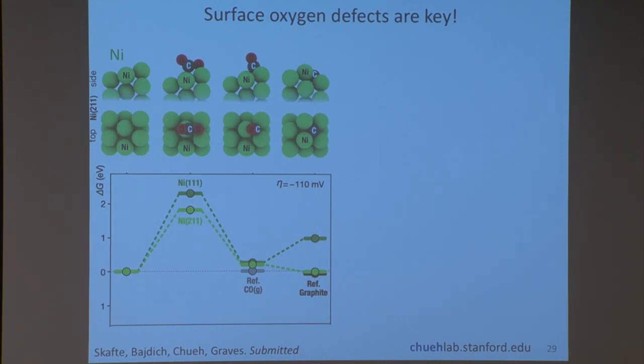And in this material, carbon is very stable. If you have this particular crystallographic orientation 211 surface, carbon is almost as stable as graphite. So that's your in your pencil. Okay? So you form carbon straight away. And this is why there is almost no barrier to forming carbon, because you start from CO gas, you come down, you remove one oxygen, you get carbon, and it's almost all the way flat. So there's no energy barrier along the way. So this is not desirable.